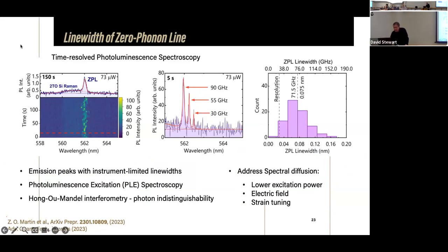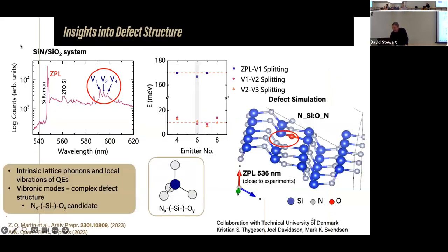Okay, in terms of understanding the nature of these emitters, we started a collaboration with a group from the Technical University of Denmark, and their simulations show that if you replace one of the atoms of silicon with nitrogen and one of the atoms of nitrogen with oxygen, and you sit at the interface between silicon nitride and silica, that's what could happen. Then you have this type of complex defect as it's shown here.